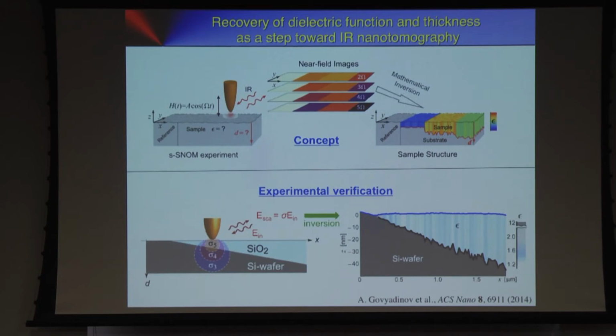So the concept is that we oscillate this tip here at a certain frequency, and then we demodulate. And we can demodulate at 2, 3, 4, and 5 times the modulation frequency. It can be shown mathematically that these images are independent. And so by inverting the whole problem, which is super difficult, we tried it for 5 years. I had a theoretician who was really expert in near-field tomography, and we didn't get it done in a global fashion. But here we got a reconstruction of this interface. We scanned a silicon oxide wedge above a silicon wafer, and then we get the reconstruction. Well, it's not really tomography, but we could localize this interface here.